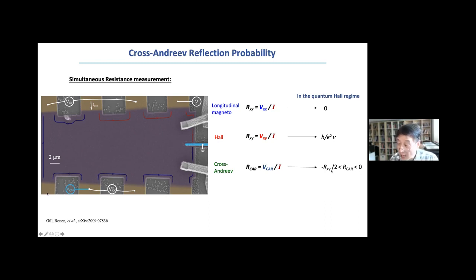It is bound by half of the Rxy if everything is completely cross-Andreev reflected. So we know that's the range of this R_CAR, and we can see the strength of the cross-Andreev reflections by simply measuring this R_CAR, right? In fact, you can just work it out with a little bit of math, and convert this R_CAR into the probability of cross-Andreev reflection per channel. That's what we call P_CAR, which is basically obtained by R_CAR divided by R_CAR plus Rxy. But as I already briefly mentioned, R_CAR is supposed to be as big as Rxy divided by 2, but typically this is a much smaller value.